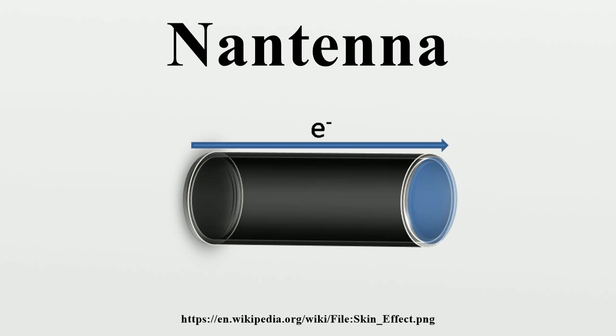Research is ongoing to tune them to the optimal frequencies for visible and infrared light. Proof of principle. The proof of principle for Nantennas started out with a 1 square centimeter silicon substrate with the printed Nantenna array filling the area. The device was tested using infrared light with a range of 3 to 15 micrometers. The peak emissivity is found to be centered at 6.5 micrometers and reaches an emissivity of 1.